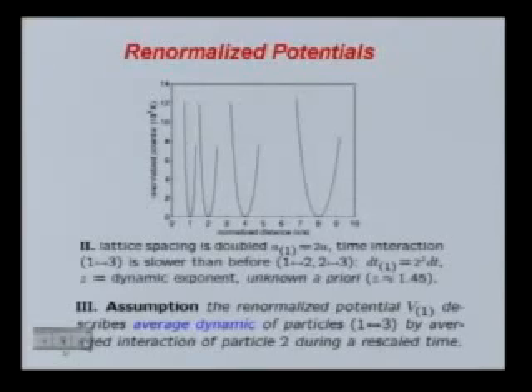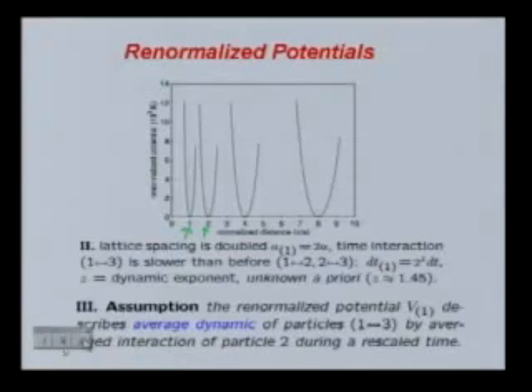And what you get at is very much what you'd expect. This is the potentials for different levels of coarse-graining in normalized distances. So if the bond length is in units of 1, this would be the normal potential. If you coarse-grain one level, removing every other atom, you end up with a potential that's twice the bond length. Because you have atom 1, 2, 3, you've removed 2, so the equilibrium distance between 1 and 3 is about 2 times the bond length. And you keep coarse-graining and end up with a potential that's 4 times the bond length, 8 times the bond length.